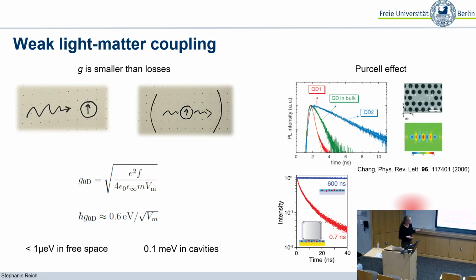So here are two very famous examples. This is kind of the defining experiment that people will always show when they talk about this. So here are quantum dots that are put into a cavity. The cavity looks a bit different than two mirrors, but essentially it's exactly the same concept. And if you have these quantum dots in free space, this is the lifetime of their light emission. And now if you put it inside the cavity and you make the cavity resonant with the transition of these quantum dots, you can see that the decay is much faster. And you can also slow down the decay by making it non-resonant with the cavity and so forth.